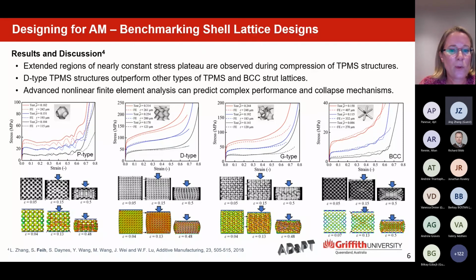So for a lot of structures, what we can see is localized shear band deformation as structures collapse. And for the best performing structures, what we see is a very uniform collapse mechanism. So that means that we have very little local variations and buckling. We have a nice plateau that keeps increasing in load, and generally those structures can carry a higher load. So here the D-type just shows very uniform deformation, while G-type and BCC structures, for example, show us localized shear bands. And the simulation is picking that up very nicely.